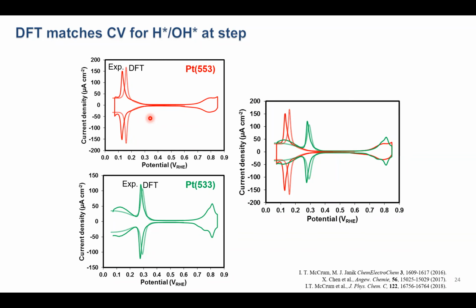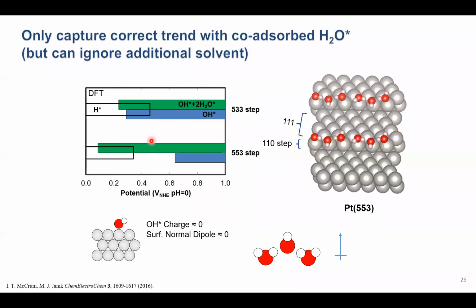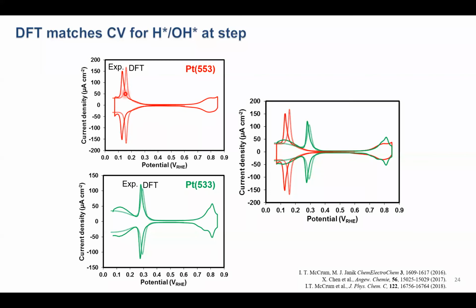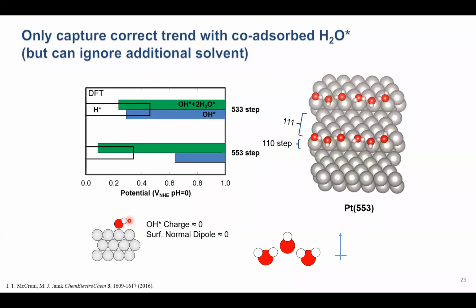What's very important to mention here is we only can capture this binding strength accurately because we considered the effect of co-adsorbed water on hydroxide adsorption. If we look at the difference between the green bars here and the blue bars here, the green is for OH with hydrogen bonded water. The blue is just for OH basically on the surface in vacuum. What we find is that when OH adsorbs in vacuum, it transfers basically all of its charge. And so it sits neutral to the surface, generates a negligible surface normal dipole moment.